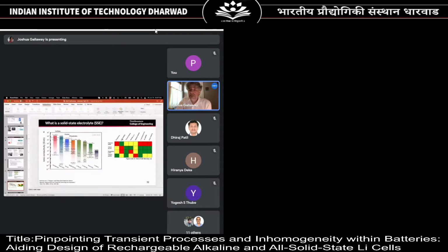These sulfides, if you expose them to humidity, form hydrogen sulfide gas, which is poisonous, of course. So these are very non-moisture stable. They're also not air stable. They're also not thermodynamically stable with lithium metal or with cathode materials. That's the reason for these yellow boxes. So these sulfides have wonderful conductivity, and there are many other things that are not good about them.